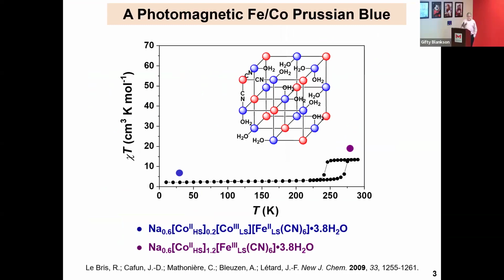So if you look at the archetypal Prussian blue, composed of hexacyanoferrate-3 and cobalt-2 centers, at room temperature, you have a purple material with lots of unpaired electrons. And so this is that species here. Everything has unpaired electrons, and you have an average stoichiometry. When you lower the temperature below a critical temperature, in this case around 250 or so Kelvin, it adopts a blue coloration, and you can see that now you've got mostly cobalt-3 and an iron-2 spin paired center. The magnetism drops. Now, if you shine light on the material, it's photoactive. That light will cause back electron transfer and regenerate this purple state, which is composed mostly of paramagnetic centers. So in doing so, you get a very large enhancement to its magnetic signal.